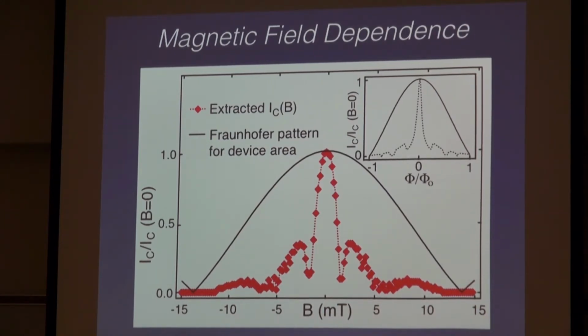For the narrowing with the magnetic field, I think we can sort of explain that by conventional means. Conventional means that we didn't appreciate at first. It turns out when you put a superconductor on a topological insulator, it changes the property of the superconductor in ways that you wouldn't expect from, say, if you put it on a metal or a semiconductor. We don't really understand that, but you take a superconductor, you put it on a topological insulator, it actually kills the superconductivity much faster than it should, based on the density of states of electrons in the system.